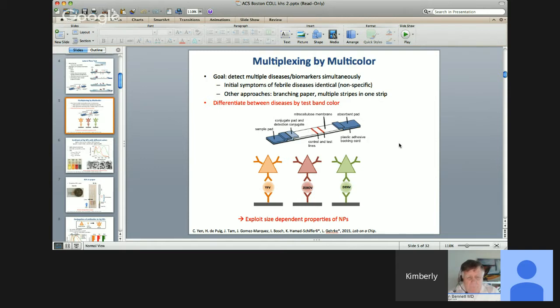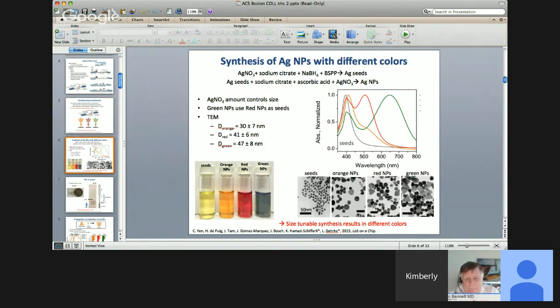So we did a proof of principle experiment to see if we could do this, and the way we did it was to take advantage of the fact that silver nanoparticles, or nanoparticles in general, can be made to have different colors just by changing their physical properties, so what size they are. And so we said, okay, let's try to do this where we can make different test line colors and have it be yellow for yellow fever, red for Ebola, and green for dengue, and see if we can exploit the size-dependent properties of nanoparticles in order to do this. Okay, so that's basically the idea of what we wanted to achieve.